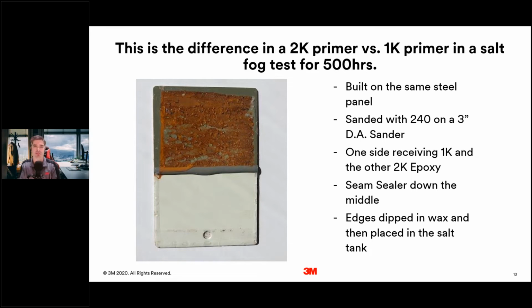And these are some of the concerning factors that we see when we're using these types of primers, because now if you take this and then double it with the fact that you might have a shadow edge where moisture can get in and start doing some damage along that surface, even though you've maybe sealed, based, and cleared over the top of that one component primer, if you have any areas that don't get the adequate mil build of paint and material on there, this is what could start.